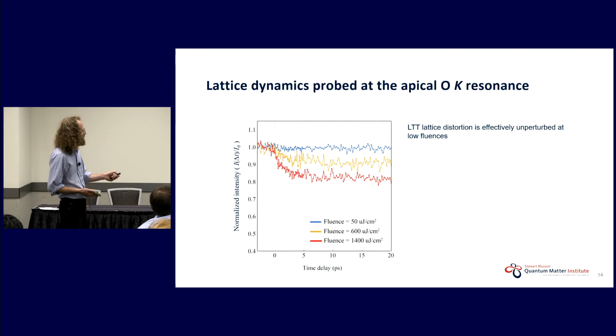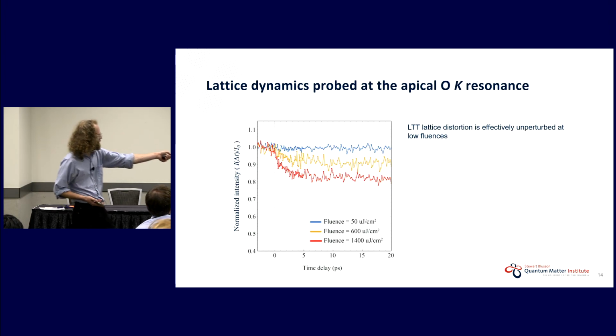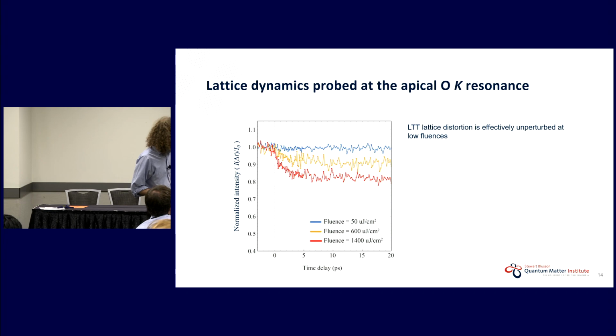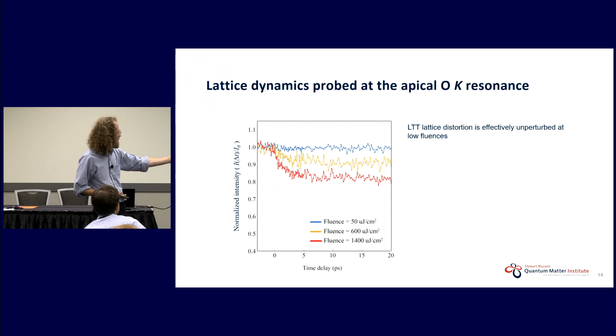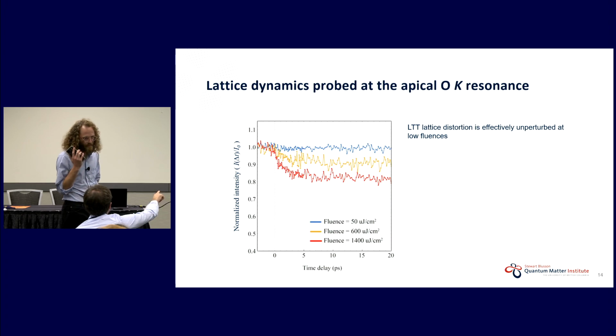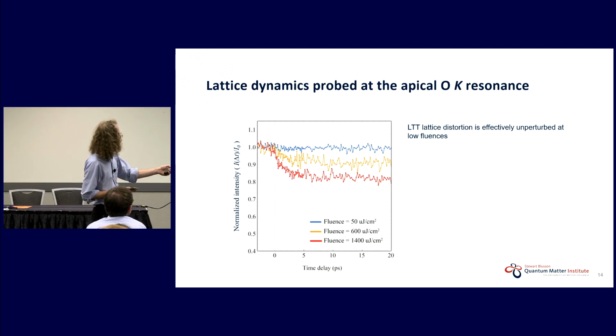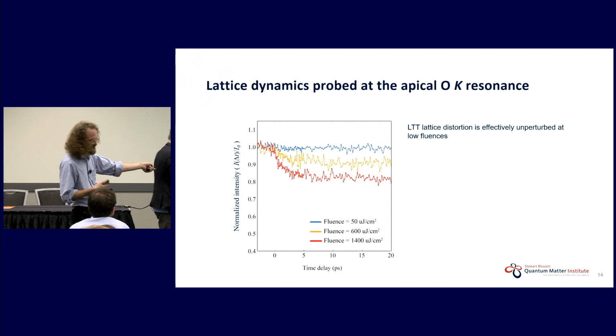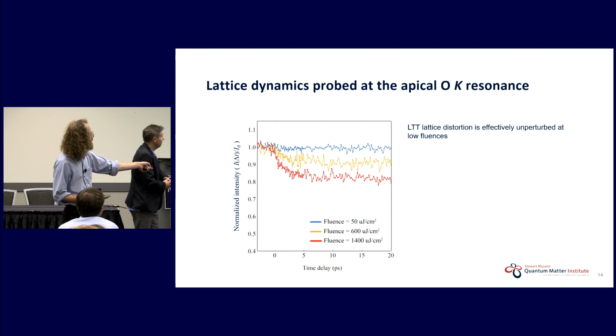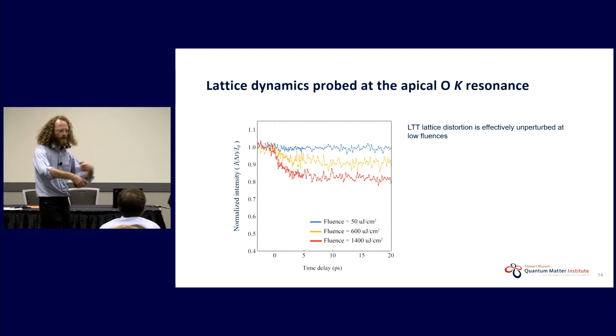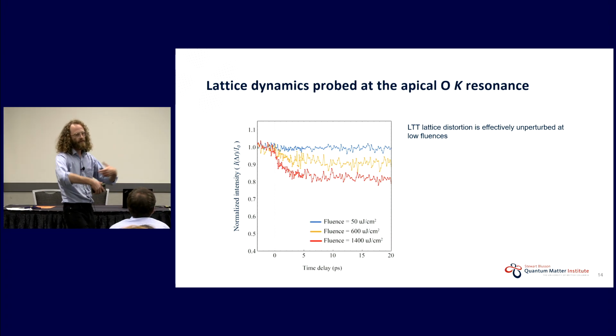Sorry, you mean the difference between this leading edge? I see there are always two time scales, right? There's the suppression and the recovery. So what about the recovery? Here you're measuring the same peak at two different energies, and in one case it's recovering very slowly, in the other case it's recovering faster. Well, this is what I would call typical of the structural response. You have this suppression which is slow, like the electron-phonon coupling, and the recovery is happening over the time scale where the phonons are exiting the beam spot. It's something that's much longer.